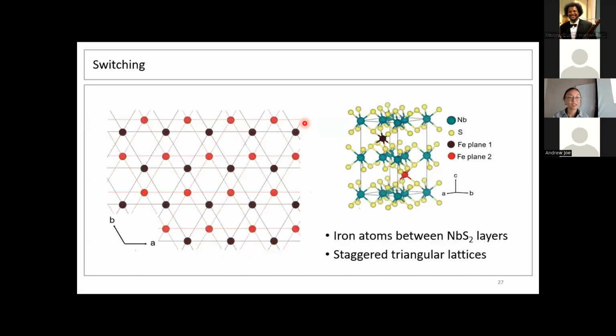Okay. So here is the system that I've been working with, and where we've been storing information. This is iron intercalated niobium disulfide. All that really matters here is that it's a layered material with iron atoms sitting in between the layers. And all of the magnetism lives on the iron atoms. That's where all of the unpaired electrons are. And they form these really nice triangular lattices within each layer.